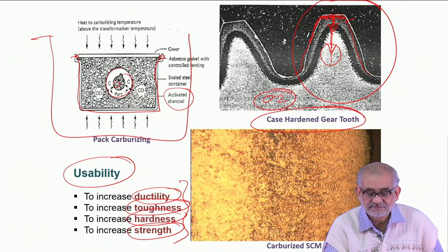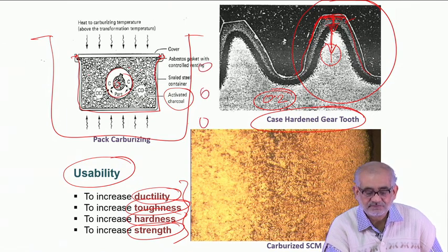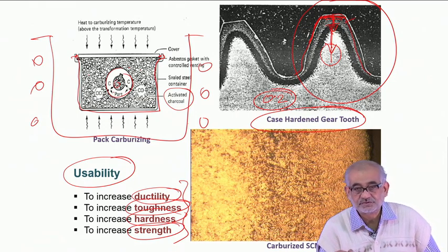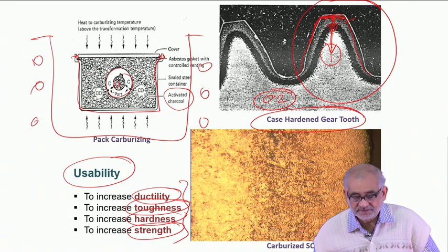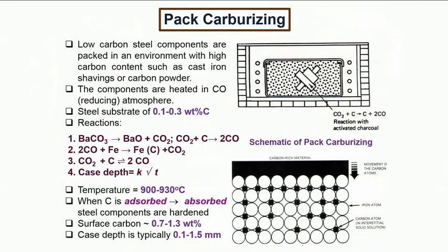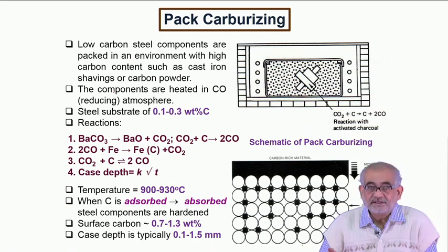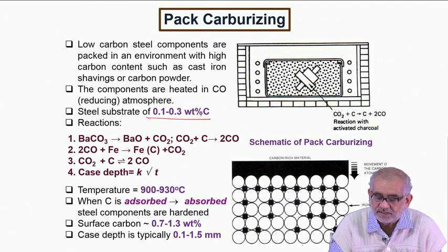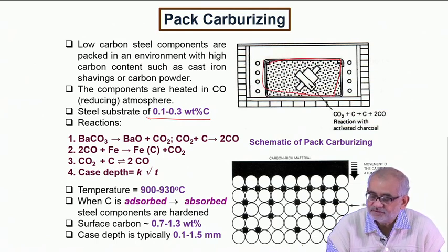So, it goes inside the furnace, and then we heat up to an isothermal condition, which could be, as I said, anything from close to 800 to 1000 degrees, depending on the initial carbon content of the steel. So, in pack carburizing, what is important, again let me repeat, is that we are beginning with low carbon stock. This is the kind of arrangement: this is the box, which is packed with this particular,